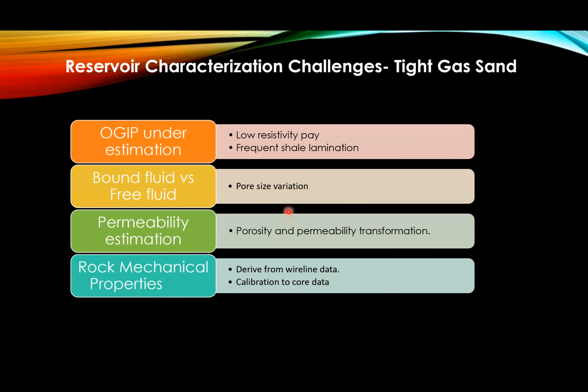So you may see a similar porosity between two sections, and one section is producing quite prolifically, the other section is not producing. That's because even if your porosities are the same, the pore sizes are different, and as a result, your bound versus free fluid are different. Same thing also, in some areas you will see very high water saturations, but you are producing no water. On the other hand, in some areas you're seeing less water saturation, but you're producing plenty of water. This is happening because even though you have the same porosity, the pore sizes are different. That is very critical information that we need to know in these tight gas sand reservoirs.